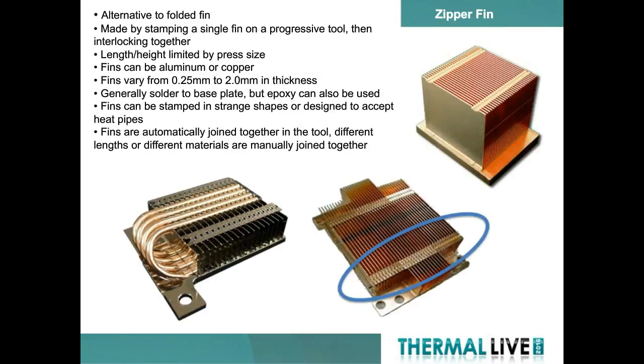But what if I want really thin fins? I want a high aspect ratio extrusion or a high aspect ratio solution, something that exceeds either folded fin or skived fin. In this case, we introduce a zipper fin. Each fin is individually stamped out, typically made out of 10 thousandths thick aluminum and or copper. The fins have an interlocking feature that ties the first fin to the second fin. These features are automatically joined together in the tooling so that when you pop this part off of the tool, it is its own fin stack. It is something easy to handle.